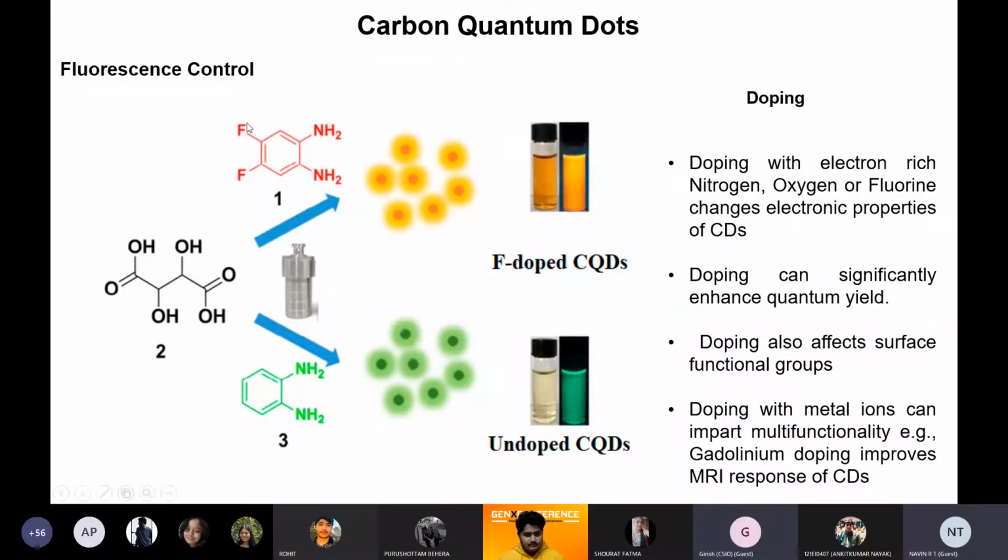So people found that when they produced carbon dots doped with fluorine, they could tune the band gap towards the red emission. So now your fluorescence goes from green to red. Your band gap energy has actually decreased, because by introducing the electron-rich carbon-fluorine atoms, they have produced more energy states where your electron can now pass on the energy and come to the ground state.